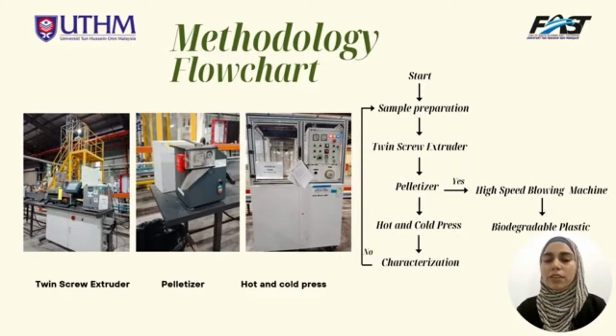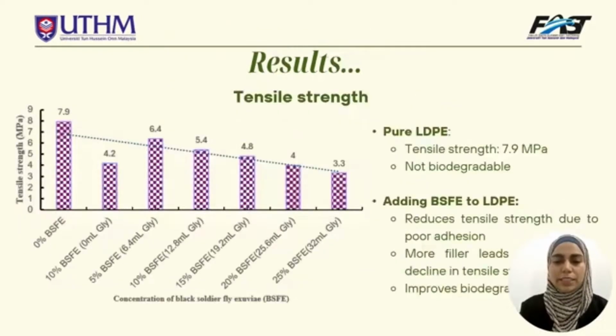We cannot directly run our formulation on a high-speed blowing machine to get the biodegradable plastic, because for running the high-speed blowing machine, the minimum requirement of sample is 3 kg. So if you have a lot of formulations, it's not recommendable to directly use the high-speed blowing machine. First, we need to follow the methodology, like we need to pass through the hot and cold press machine. After knowing the best formulation, for commercialization, we can pass it through the high-speed blowing machine to get the biodegradable plastic.